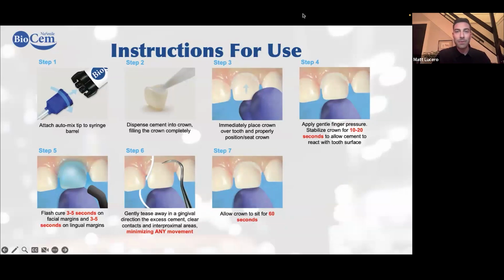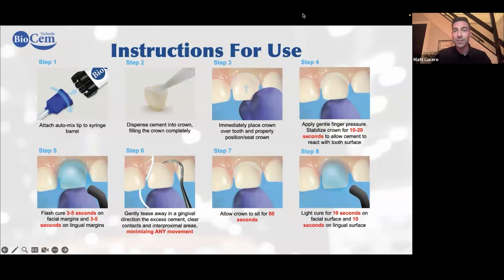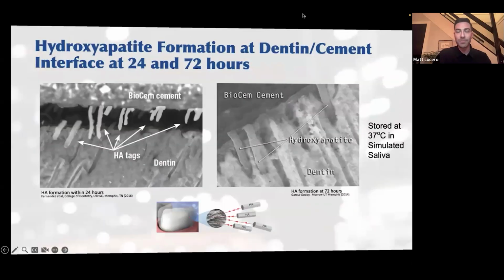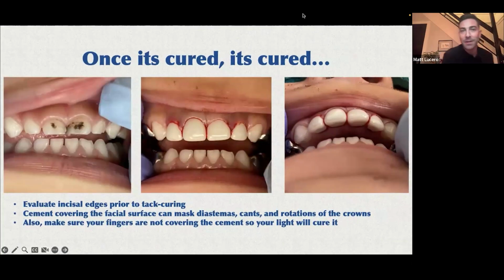But if we're doing it quickly, we may want to give it a few more seconds to let that bioactivity continue to penetrate those dentinal tubules. And then we give it a final cure, about 10 seconds on the facial and lingual surfaces. And there's the hydroxyapatite formation that you can see on a scanning electron microscope there.